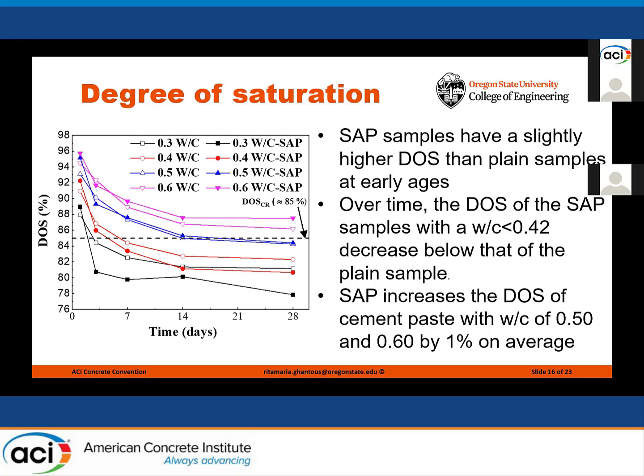And then we can see that the SAP addition to sample with high water to cement ratio slightly increase the degree of saturation at the different curing ages, while for samples with low water to cement ratio, the SAP increases the degree of saturation only at early ages, but it does even decrease it at later ages.